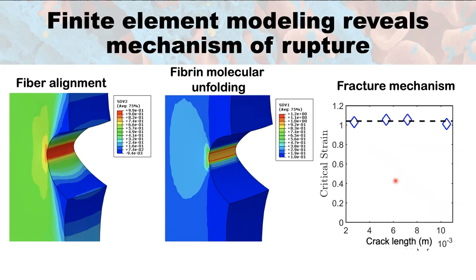And ultimately, the model shows us that when the rupture process happens, it happens at a critical strain ahead of the crack tip that is independent of the crack length. And importantly, this points to the mechanism of rupture, that is a critical fracture strain that's driving the process and not, say, diffuse damage that's happening to the clot. And importantly, this maps to the rupture of individual fibrin fibers that have been shown by other researchers as well. So pointing again to what the mechanism of fracture is.